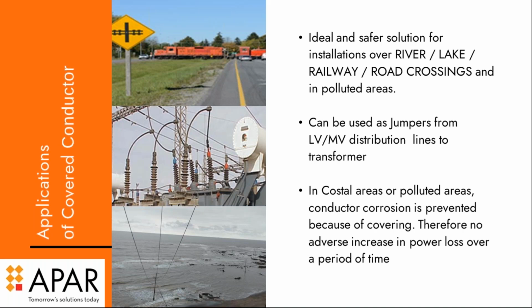Then it is also being used in the coastal areas and the highly polluted, corrosion-prone areas, industrial areas where a lot of industries are there. These are the places where you can use the covered conductors. They are an excellent application for these areas, because of the salty environment, there is no effect on the conductor inside the insulation, and it is also a watertight conductor, so it can serve a whole life of 30 to 40, 50 years, without any damage from corrosion or the saltiness of the water or any pollution in the network areas.